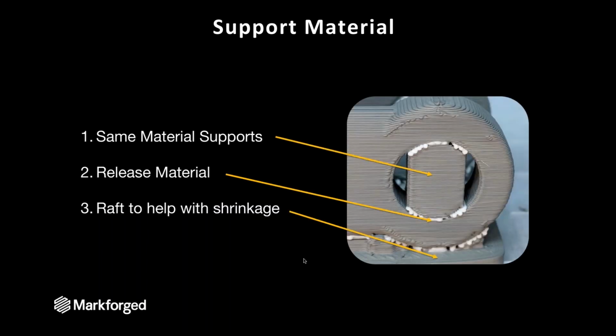So this is a little image of what our support material looks like. If anyone's familiar with our composite material or parts, we use the same material like plywood supports, and we do the same thing with metal as well. So we use the same material, 17-4 being our most common one, and then we also have a release material, and this release material turns to a fine dust, which then allows you to tap out all of the supports post sinter. Also, we print all of our parts on a raft. This allows us to have uniform shrinkage and make sure all of our parts shrink uniformly, so we can get your part as dimensionally accurate as possible.